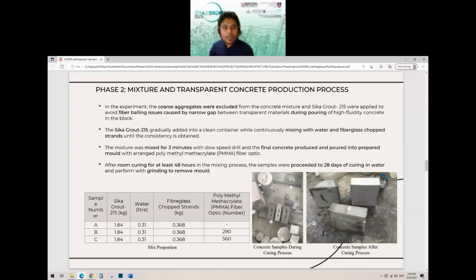After the final concrete was produced, the transparent concrete will continue with the process of curing for at least 48 hours and proceed to 28 days of curing in water, and grinding is performed to remove the molds.